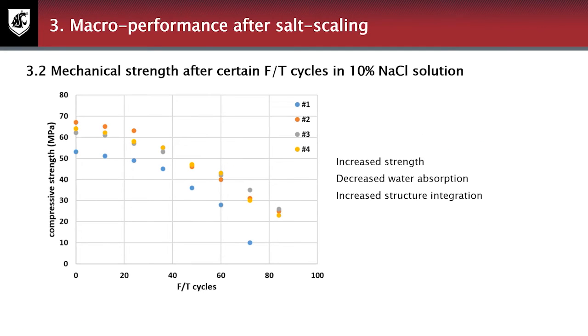Here we test the strength after certain salt scaling cycles, and we find samples 2, 3, and 4 are better than the original sample. More specifically, we can say sample 3, the grey dots. In the beginning, the strength is a little bit lower than sample 2 and sample 4, but in the later age, the strength is a little bit higher. This result indicates that fiber did have some benefits on increasing the freeze-thaw or salt scaling resistance.